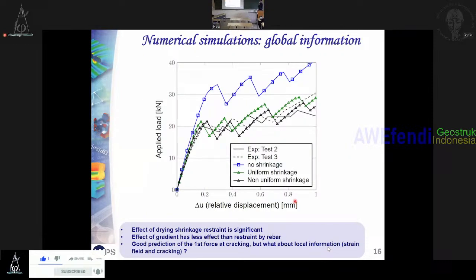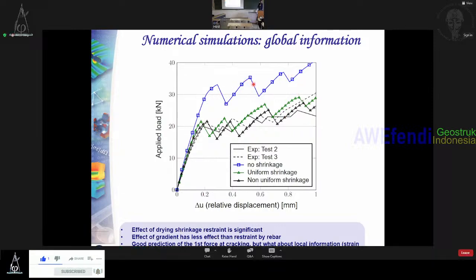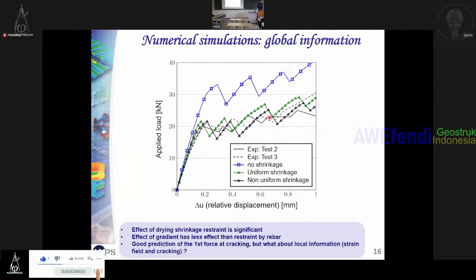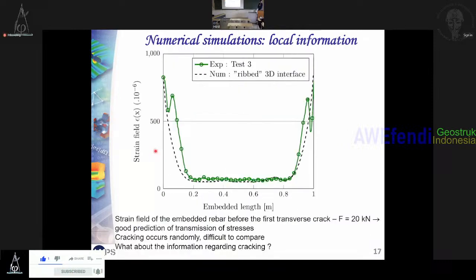Now when you perform the numerical simulations, here you have the experimental results, and here was the previous numerical result. So we have an overestimation of the load. And here, if you take shrinkage into account, you can see that you are better able to predict the behavior. We have also tested the effect of the gradient, because you have the restraint of shrinkage of concrete by the rebar, but also the gradient. You can see that the effect of the gradient is not so important, but in our opinion it is important, in order to predict the behavior of concrete structures, to take into account the fact that you may have initial tensile stress inside the specimen. So this is for global information.